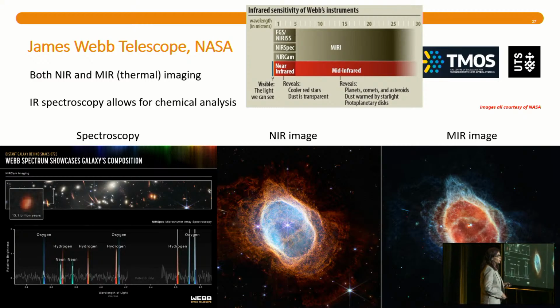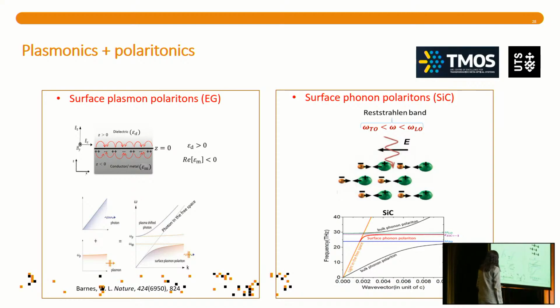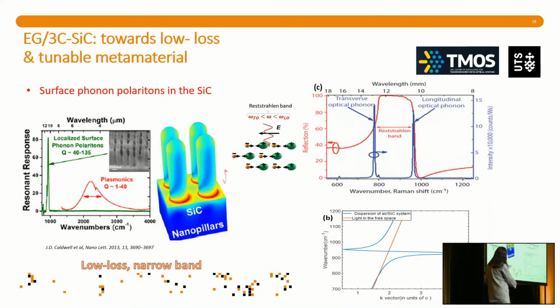One of the problems is that most MIR systems have to be cooled down, and so they're bulky and such. So we're working towards making that much smaller and portable. How are we doing that? Well, we count on a combination of surface plasmon, which is supported by graphene, and surface phonon, which is supported by silicon carbide. Silicon carbide has a covalent bond, so like a spring mass here. And it turns out that silicon carbide responds in the Reststrahlen band, where it behaves basically as a metal. Silicon carbide is in this region between LO and TO, and that's exactly in MIR, basically.